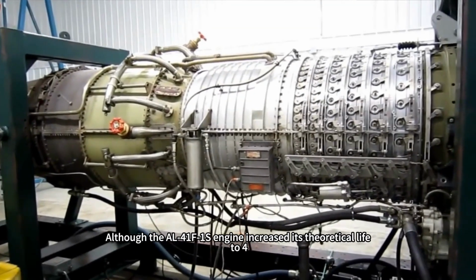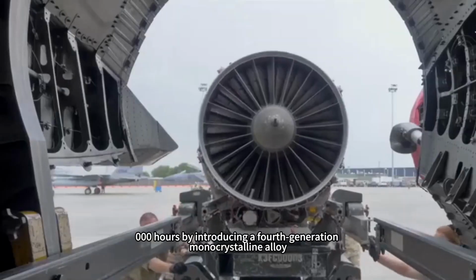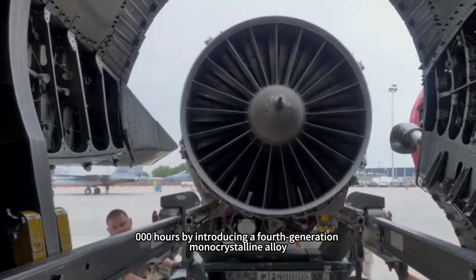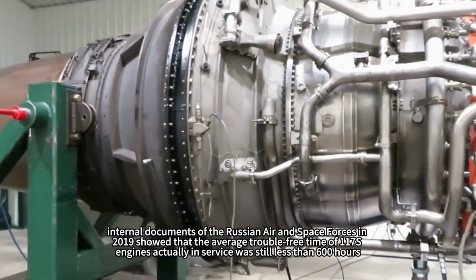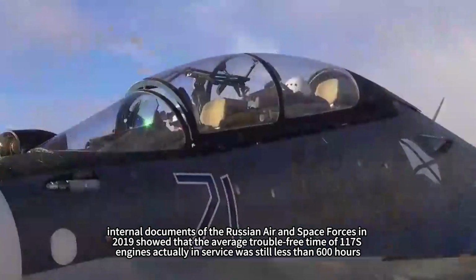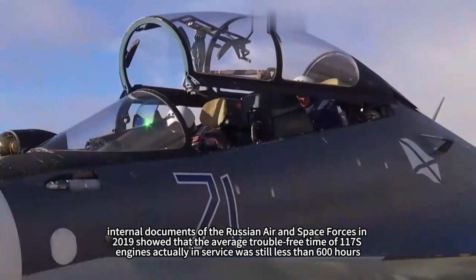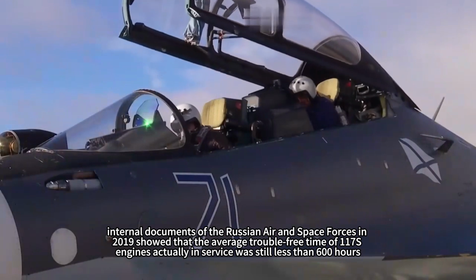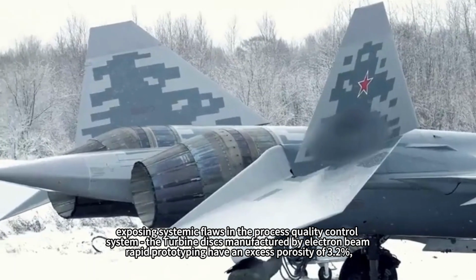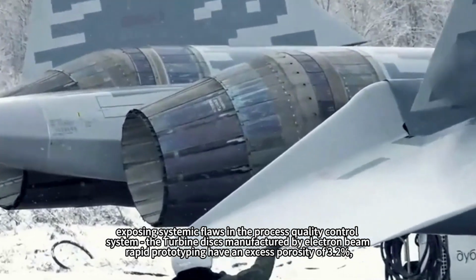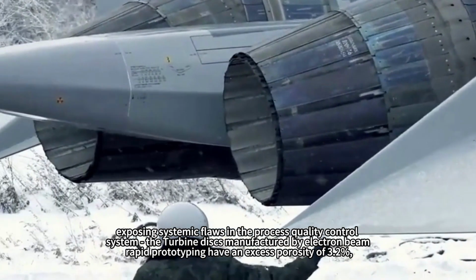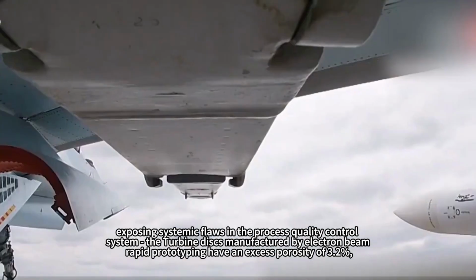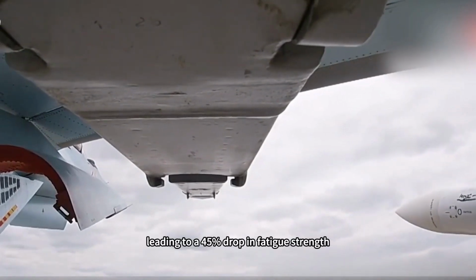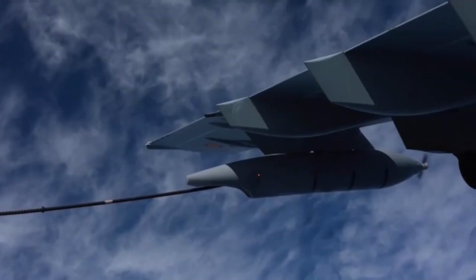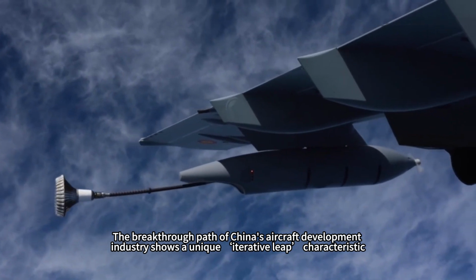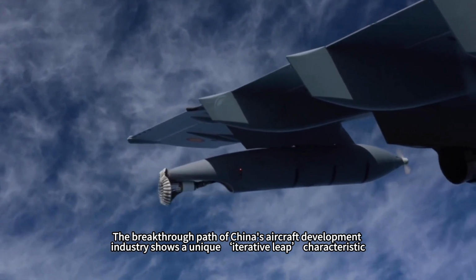Although the AL-41F-1S engine increased its theoretical life to 4,000 hours by introducing a fourth-generation monocrystalline alloy, internal documents of the Russian Aerospace Forces in 2019 showed that the average trouble-free time of 117S engines actually in service was still less than 600 hours, exposing systemic flaws in the process quality control system. The turbine discs manufactured by electron beam rapid prototyping have an excess porosity of 3.2%, leading to a 45% drop in fatigue strength.